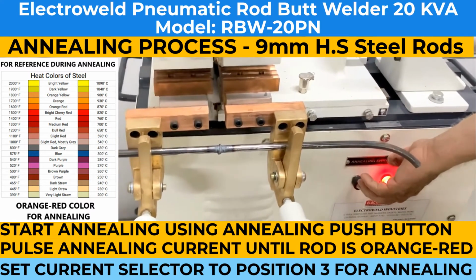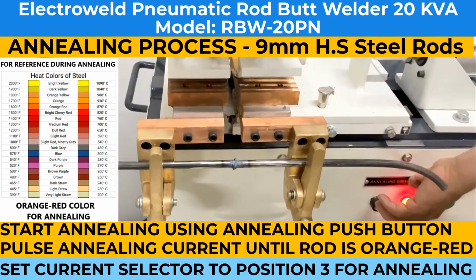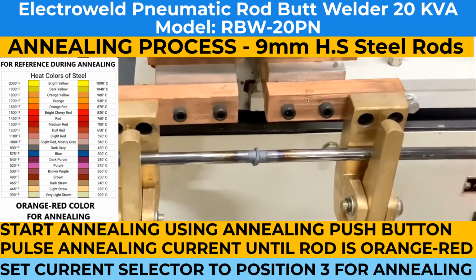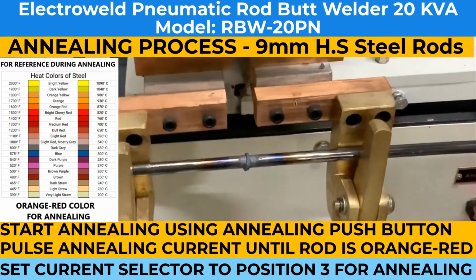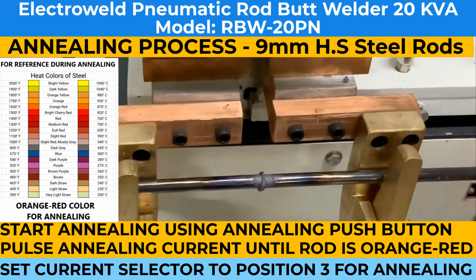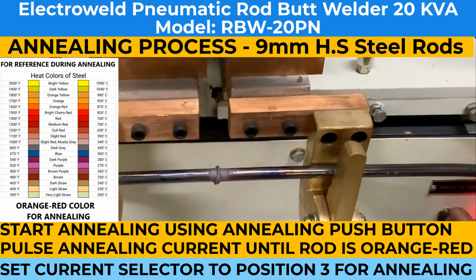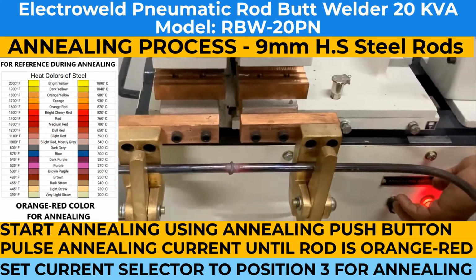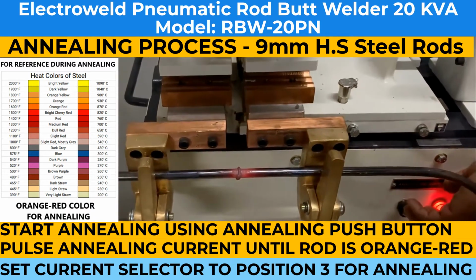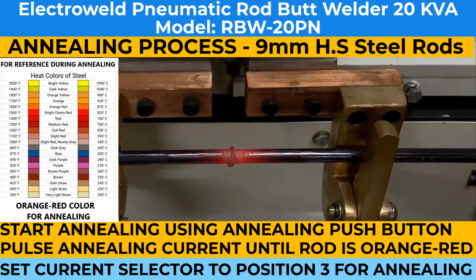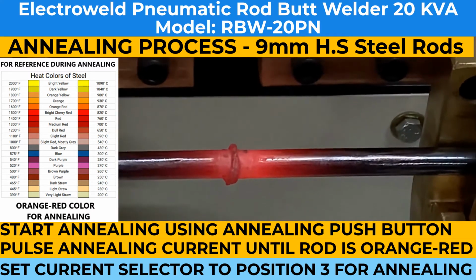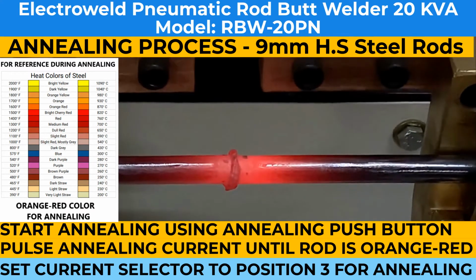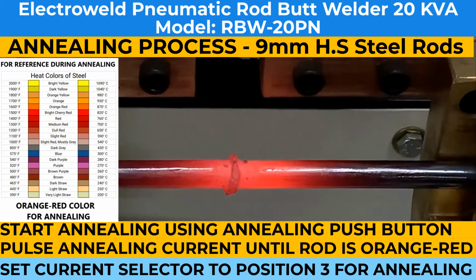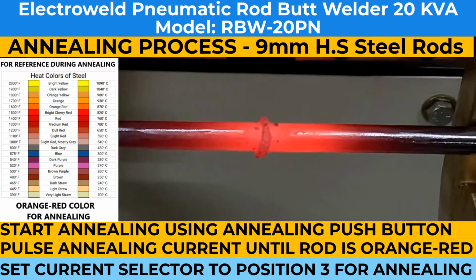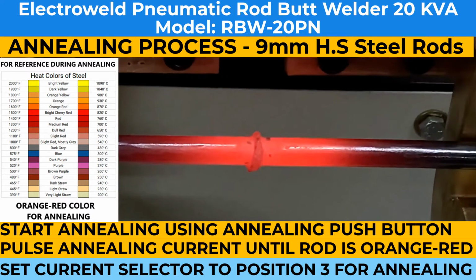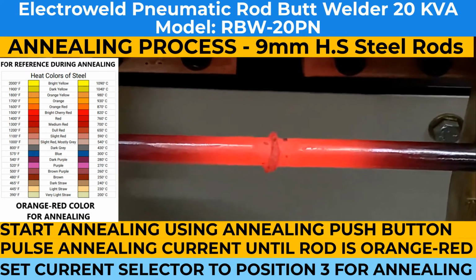till reddish tinge appears and the scales are visible near the weld. The welding should take more time so that it's slowly for the proper weld joint to get annealed. This is necessary especially for the high carbon rods, otherwise the joint will break in the dies. You should heat up slowly till reddish tinge appears and the scales are visible near the welded joint.